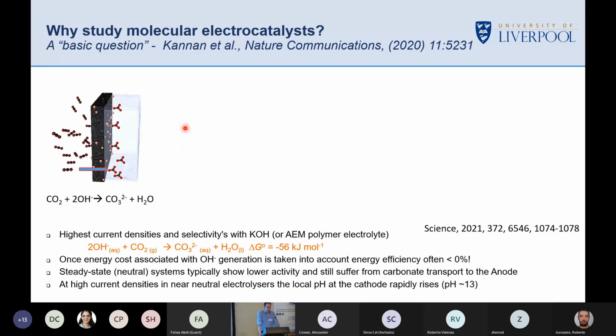We've now got to take our CO2, purify it often, and place it into our device. And here we're going to talk mainly about gas diffusion electrodes. So the CO2 is going to be brought through the back of a porous electrode. And I should just say this is important, otherwise we can't get to the high current densities. If we use a conventional planar electrode in liquid, the solubility of CO2, in the order of 30, 35 millimolar, means that we can't get a stable current density of more than 10 to 15 milliamps per square centimetre unless we really start to stir the solution quite hard or agitate it in some way, which of course comes with an energy cost.